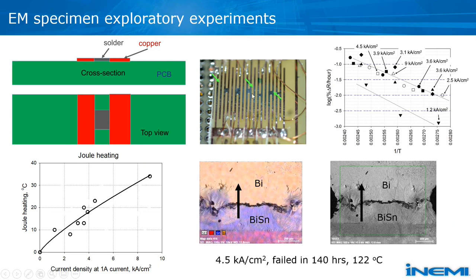So what we did was we formed solder bridges between the copper lines. If you look at the picture on the left top, the red are copper lines, you have the top view, and we formed a solder bridge between the copper lines. And at the very top we have the cross section, so you can see the copper lines and the solder in between. So now we can pass current through the solder and look for electromigration. And the picture on the bottom right is a scanning electron micrograph, which shows that bismuth moved up because of electron flow, and there's a crack in the joint.